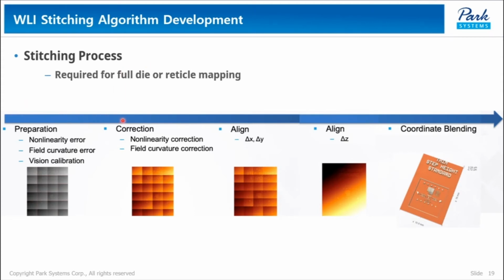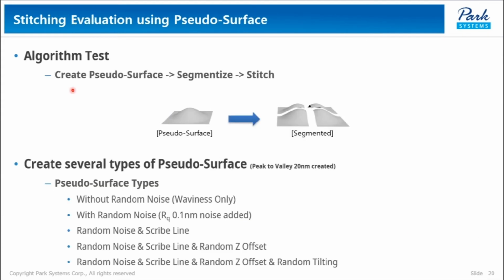These are the basic processes of stitching. In preparation, define non-linearity and field curvature errors in addition to vision calibration. After correcting non-linearity and field curvature errors, we need to align X, Y, and Z as a whole image. Then, we use an advanced flattening process to minimize the errors. We created pseudo-surfaces, segmented them, and stitched them again to evaluate the stitching algorithm. For simulation, we create several types of pseudo-surface with variables of without noise and with noise, the presence of scribe lines, Z offset, and tilting. It is easier to understand by seeing the following figures.